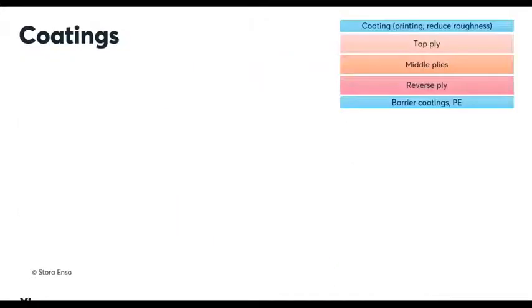After the paperboard is made, dried, and rolled, the next step is to add coatings as appropriate. This includes coatings on the top ply that further reduce roughness, along with printing, as well as coatings on the reverse ply side. These latter coatings include polyethylene, which provides water resistance and serves as an adhesive layer for the aluminum layer, which acts as a barrier against gas diffusion, water vapor, odor, and light.